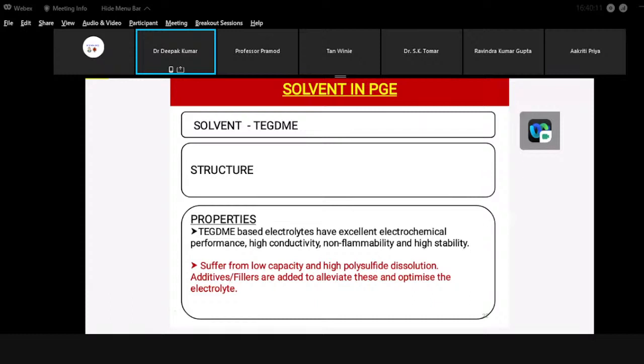TEGDME is used because of its excellent electrochemical behavior. It is able to support high ionic conductivity. It is less flammable, or you can say non-flammable. That depends on the choice of the salt and the choice of the polymer also. And it is very stable. However, because nothing has all the properties, there are always some drawbacks. The drawbacks include the low discharge capacity if we are utilizing this system in a battery, and the polysulfide issue is also there. To address this, either blends are formed, or some people add other additives as stabilizing agents, and many times fillers are introduced to alleviate these issues.